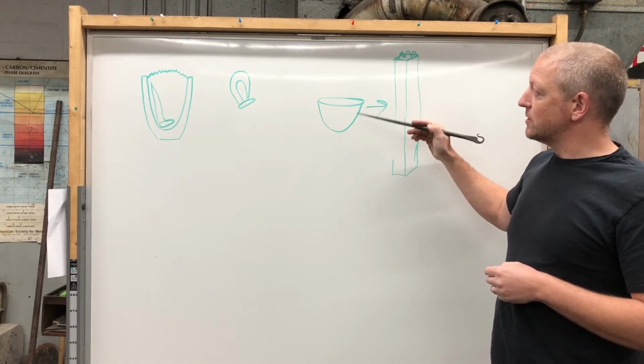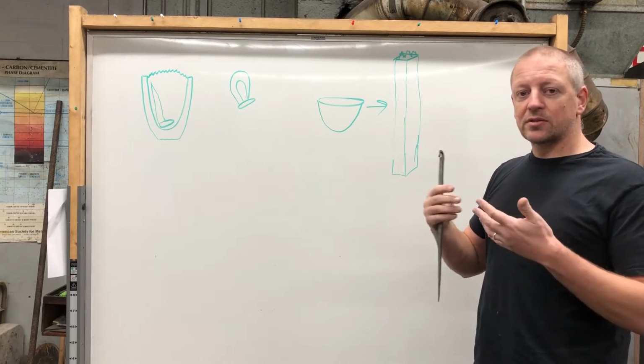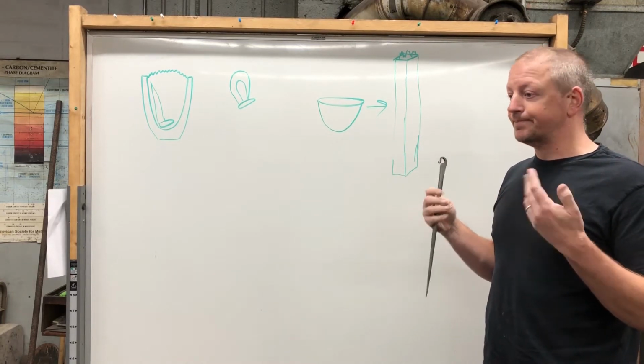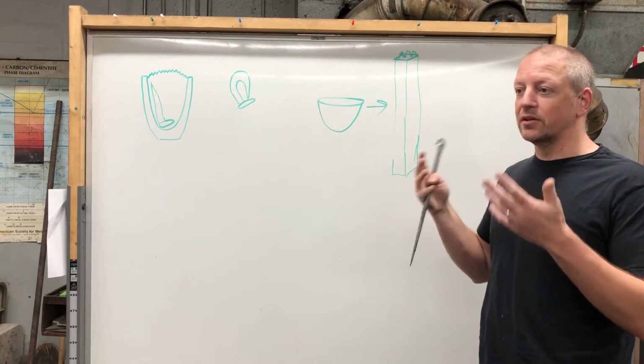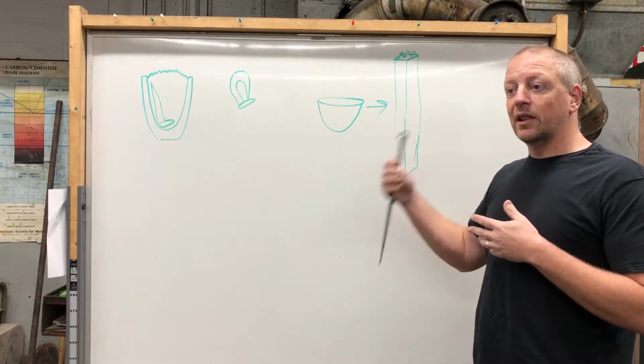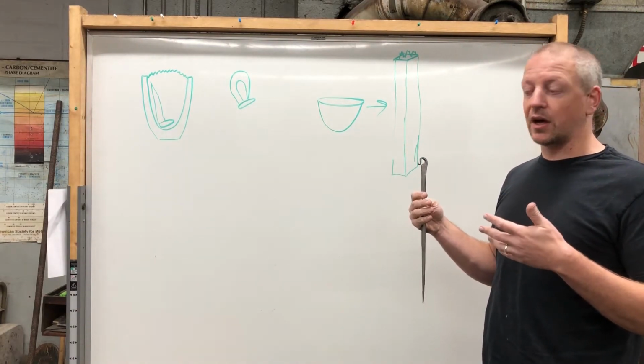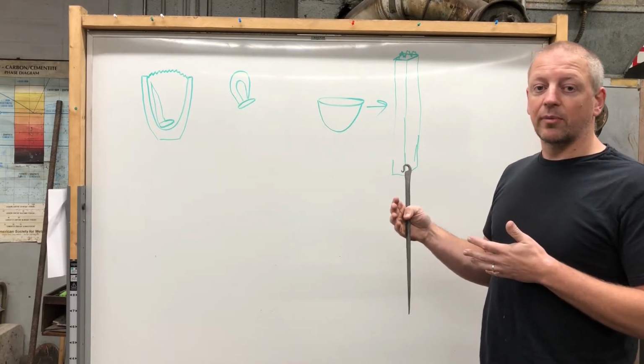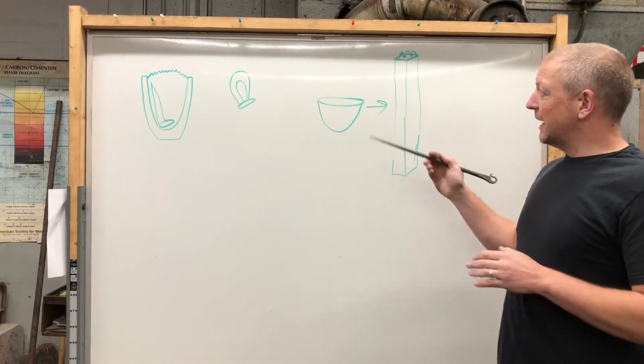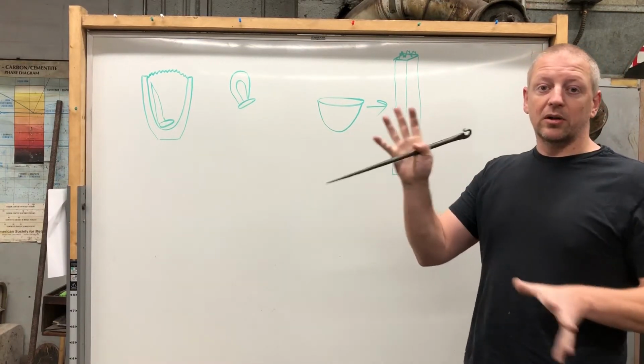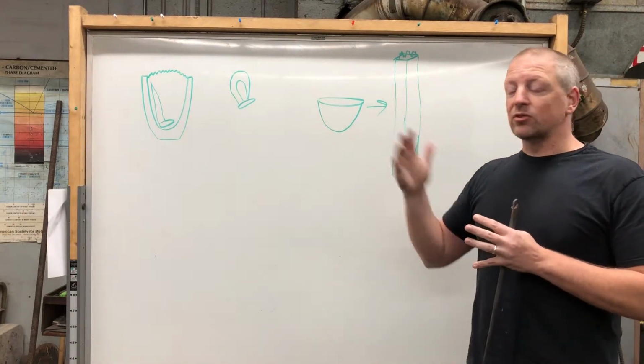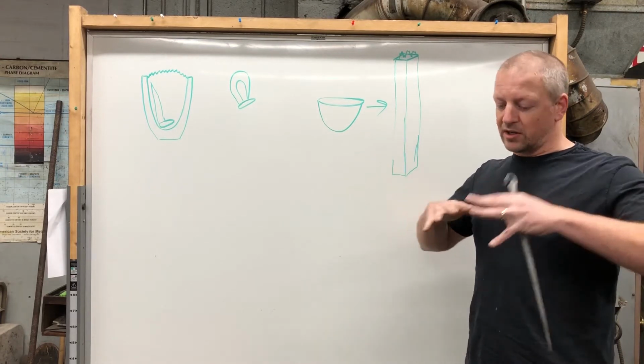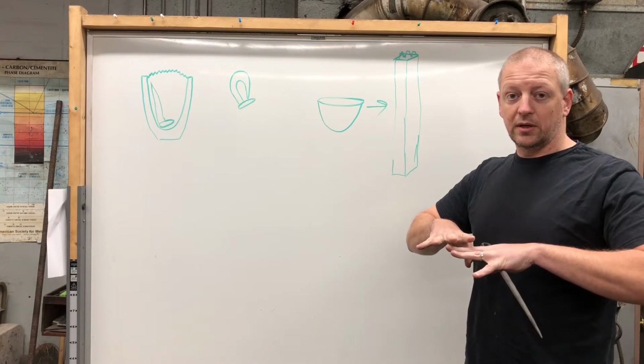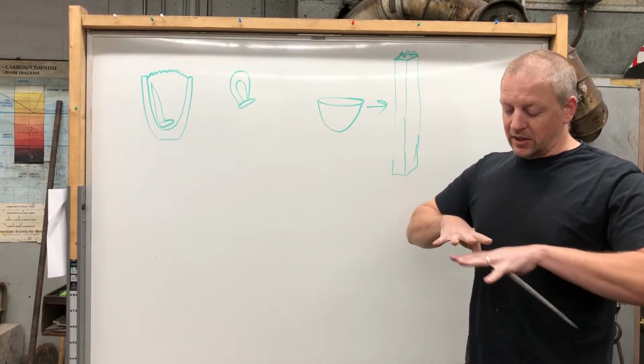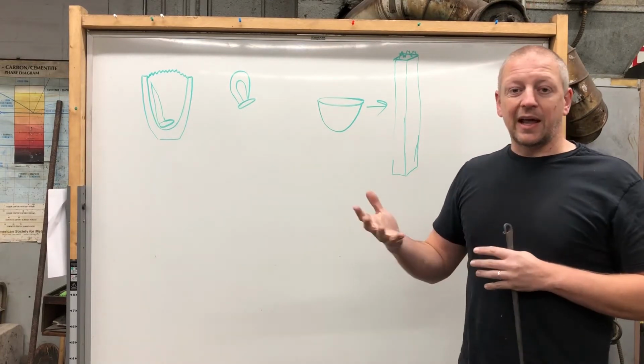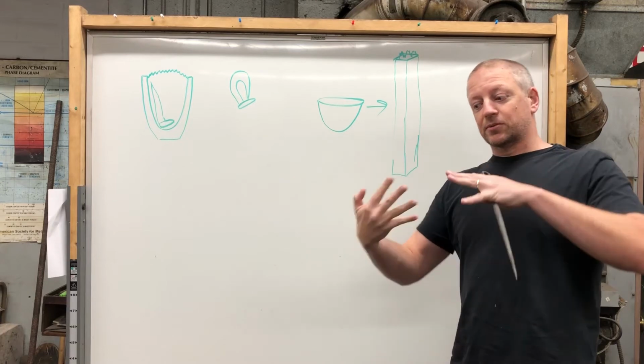What I have found over time is that these dendrites that form, and dendrites are just a natural form of solidification. It's the crystals on your windshield. Basically anytime you see a liquid becoming a solid, in most cases, if it's not a pure substance, it will develop dendrites. And those dendrites start in a single point and spread in all directions. So there's not much organization to it. If you look at pictures of dendrites, they kind of look like they're forming a grid. But when you look at it more closely, you realize that it's like a grid here and then a different grid over here. And now imagine that's three-dimensional. So you've got grid coming this way, that way.